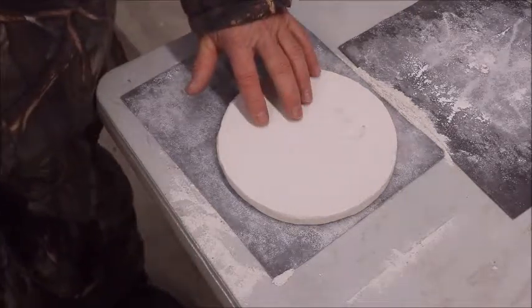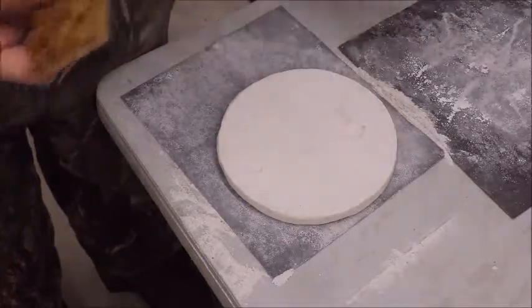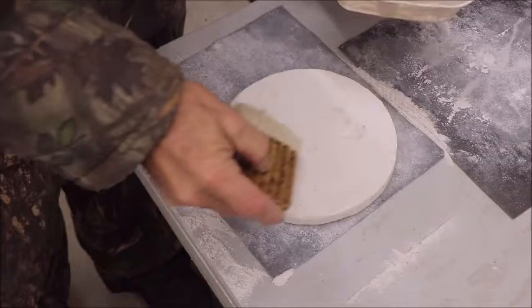Okay, there are a couple of things you can do from this point. If you wanted to, you could take some kiln wash — it's just this pancake batter consistency stuff — and you could paint this whole thing with kiln wash. These little divots here you could just keep filling them up with kiln wash until they get kind of even. It'd take three or four or five applications, then you could sand it all down and use it just like it is. Put two coats of kiln wash after you get the holes filled in.